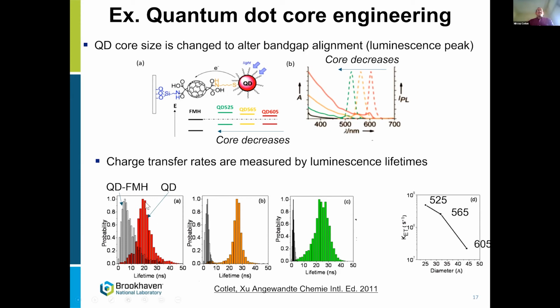These distributions are lifetime distributions, which are indicative of the strength of the electron transfer. The ones colored relate to single quantum dots, basically. So if you look at the lifetime values here, the mean peaks for red quantum dots, when I say red emitting, yellow and green, they are pretty much similar. But when we couple them in the donor acceptor pairs, basically we see stronger quenching with decrease in the size, basically.